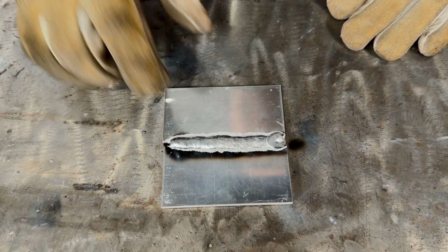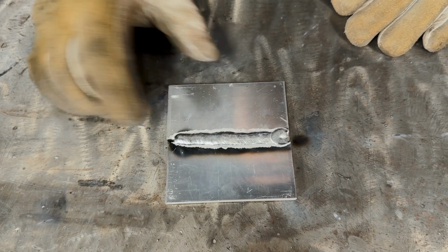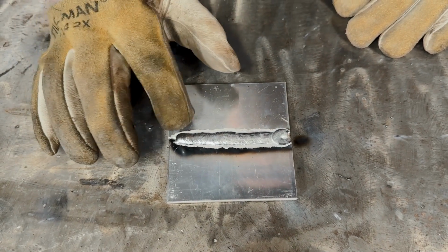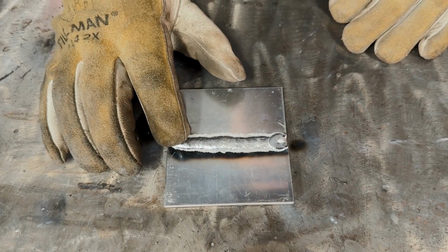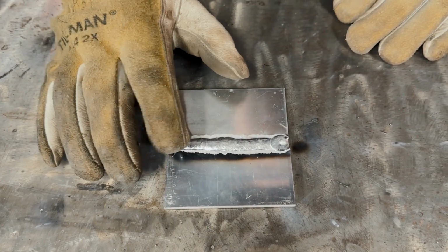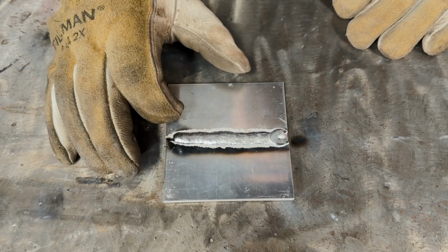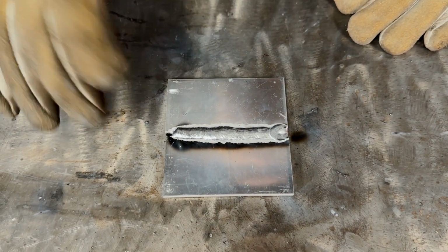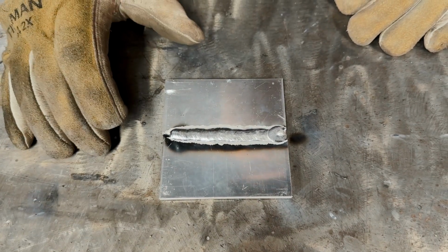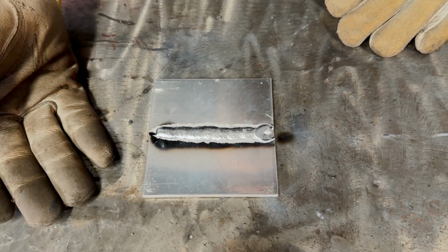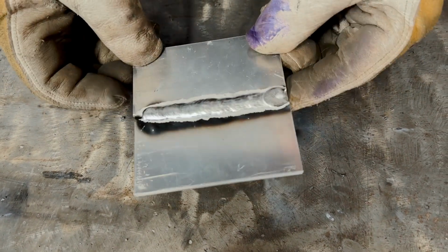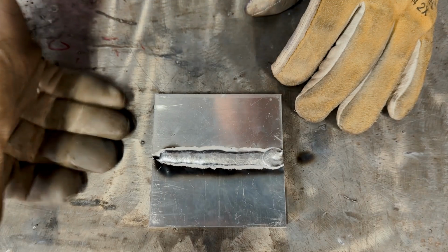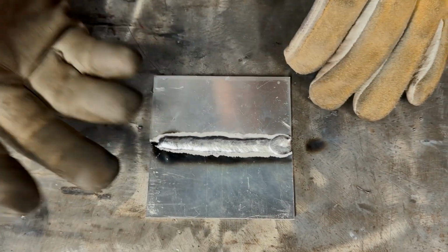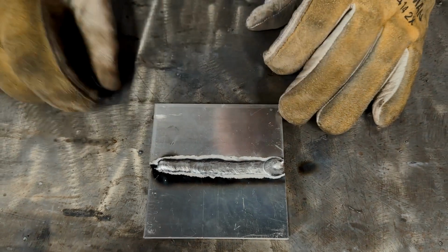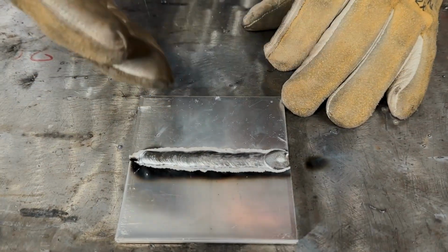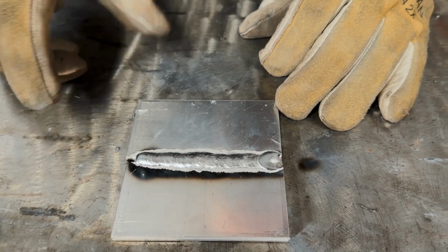So you can tell my gun angle was a little bit better. There's actually some soot on this side. And also, you have a little bit of a cold start and you heard a couple pops in the beginning. Maybe it could have taken another 0.3 volt or something. This is you, the operator, depending on what alloy you're welding, what wire you're using, if you have a heatsink under it or not. If this was propped up on some TIG rods, I'm pretty sure it would have been hot enough. The heat sink here pulling the heat out, it could have used a little bit more voltage. This is 3003 material. Different base alloy requires different small adjustments.